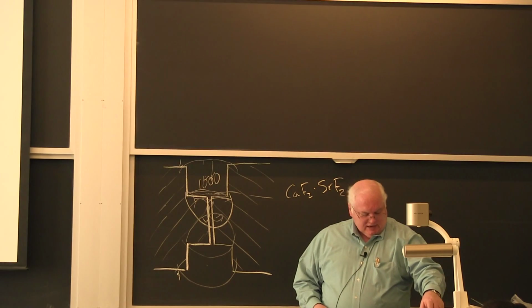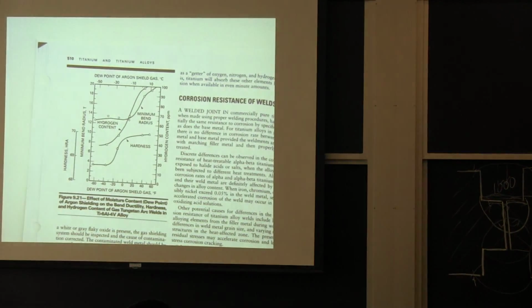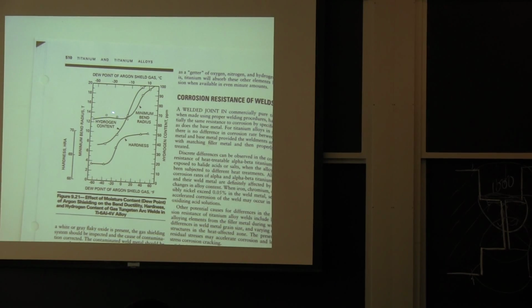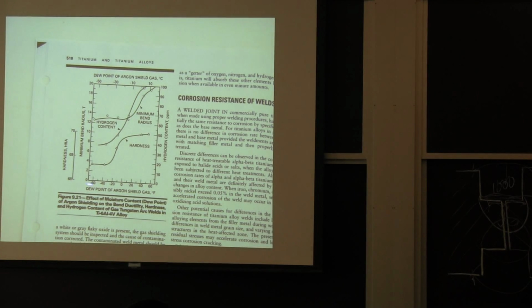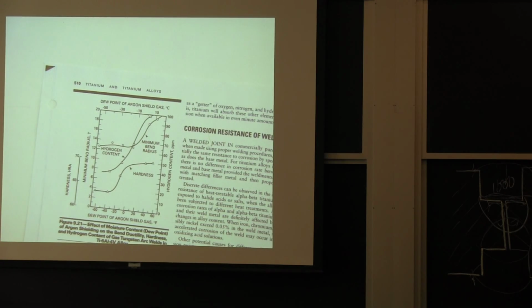I told you it's not that it hates hydrogen. You can actually tolerate a fair amount of hydrogen. This is dew point of the argon shielding gas versus hydrogen content. Here's 60 parts per million and so on. If your dew point gets very high, all of a sudden your hydrogen goes up, your hardness goes up, your minimum bend radius, you lose mechanical properties. Okay? It doesn't crack, but you lose mechanical properties. You've got to do a lot of things to shield the titanium when you weld it.